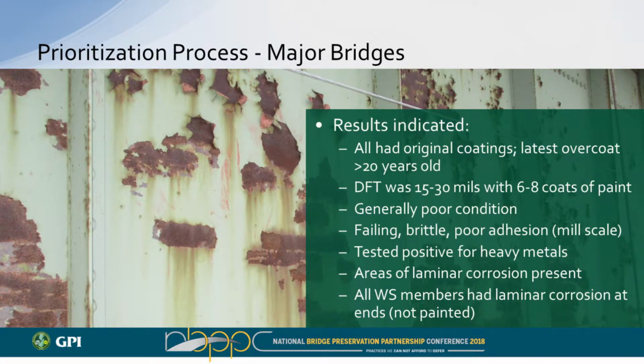Laminar corrosion was present throughout. There were section losses. The weathering steel members we found generally limited to the beam ends and areas that were exposed to, say, a splash zone is where that laminar corrosion was present. Where there weren't chlorides introduced, the patina was in good shape and was still protecting the steel. It was just where those deck joints had failed or were getting splashed with the chloride, especially during the winter months, areas that we needed to focus on.